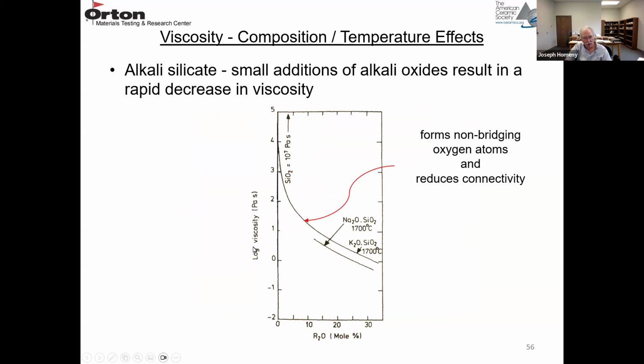So here's another log viscosity plot. This time we're plotting it against the mole percent R2O additions. And both of these plots are at 1700 degrees C. So if we put SiO2 on this plot at 1700 degrees C, its viscosity is 10 to the 7, and these are in Pascal seconds. So it would be up here somewhere, the viscosity of the silicate glass.